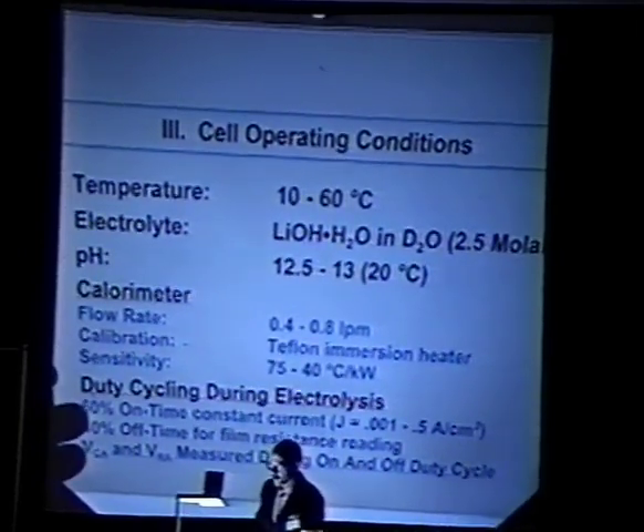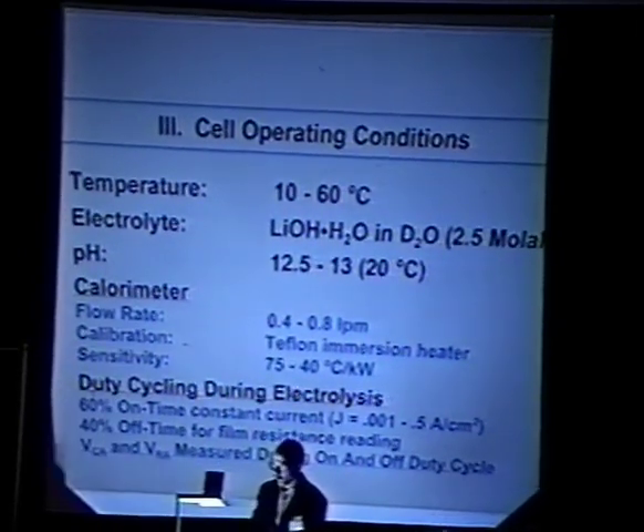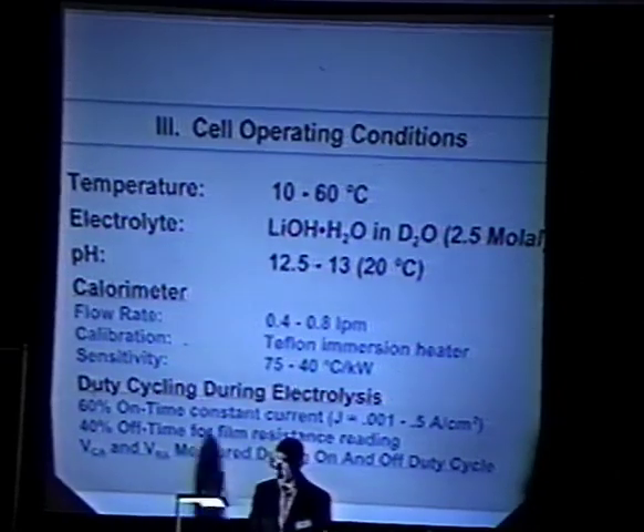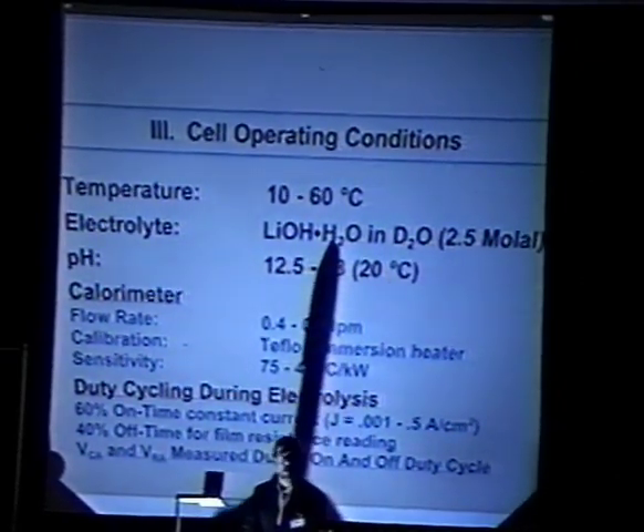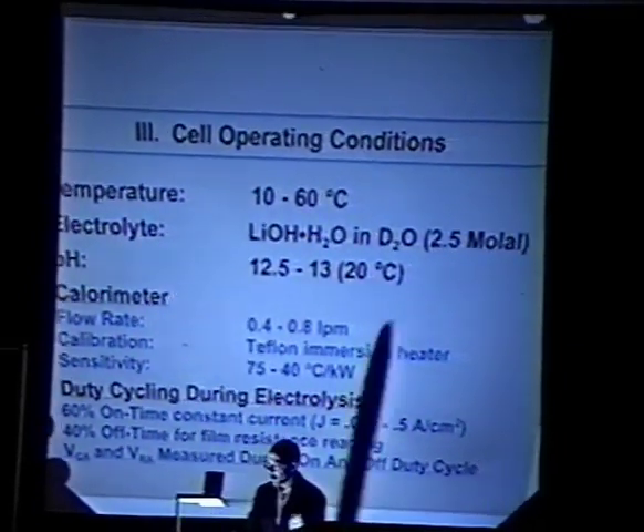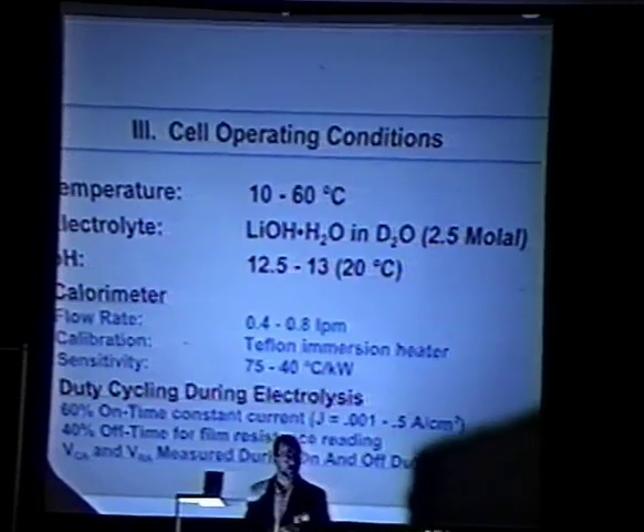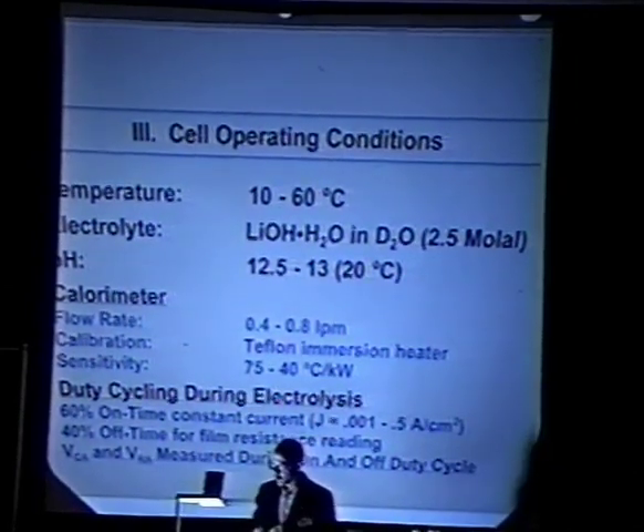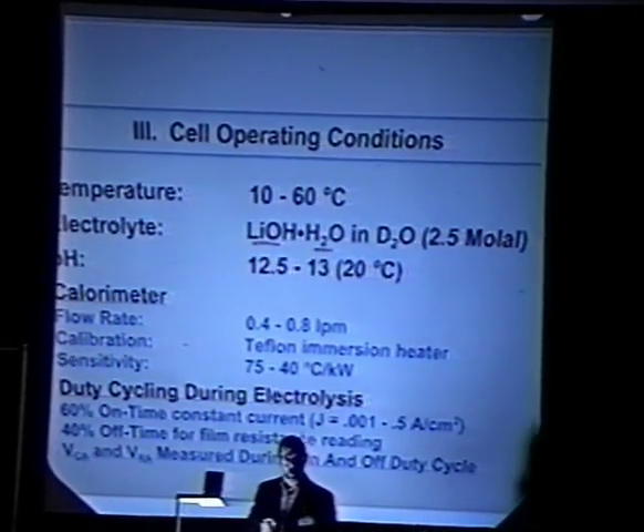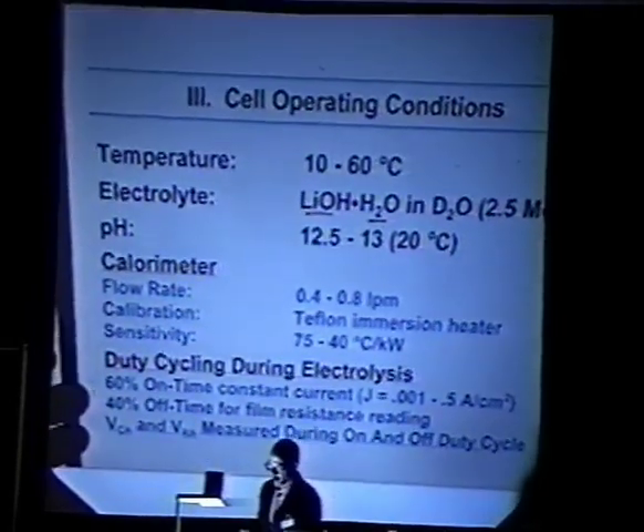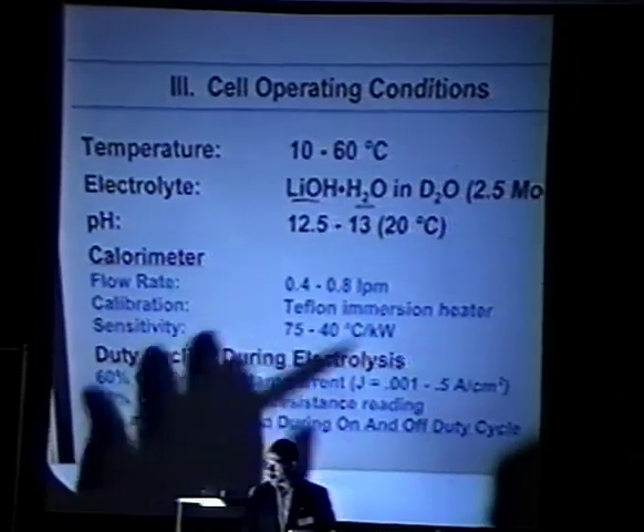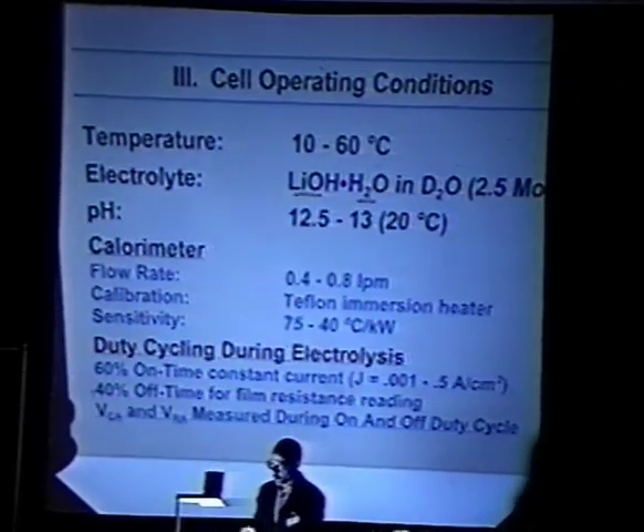The electrolyte is also a little different than several I've seen before. It's a lithium hydroxide monohydrate in D2O. So at the very beginning, I have H2O in the system. In fact, it's about a 5% mole fraction. It comes out to a 2.5 mole solution in terms of concentration. So I think that's a key feature that may be different from several others that have been done. Highly concentrated lithium hydroxide. The pH runs 12.5 to 13 at room temperature.